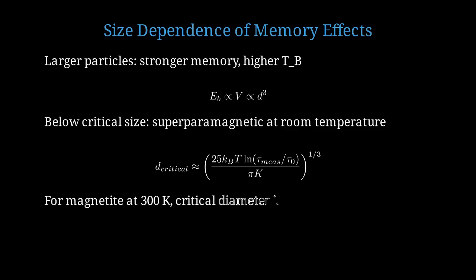For magnetite at room temperature, this critical diameter is approximately 8 nanometers. Particles smaller than this show no magnetic memory at room temperature.